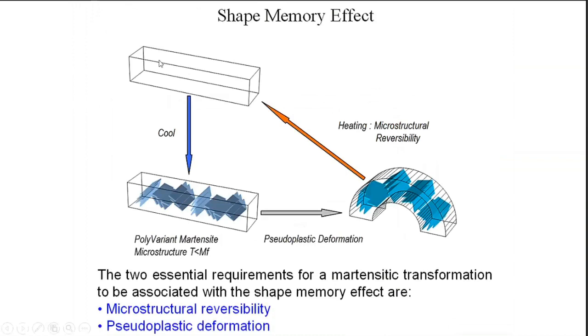So you start with an austenite, let us say a crystal, and when you cool it, you get a polyvariant martensite microstructure. What this polyvariant means is you have a lot of orientation variants. We said up to 24, and you've seen an example in the case of copper, zinc, aluminum, and nickel titanium. You have a lot of variants in the microstructure which form the self-accommodating martensite. And what you've done is pseudoplastic deformation. We've done a deformation which is very different from conventional deformation, and you've got a macroscopic shape change, as you've seen in the case of the flower, which was crushed into a bud. But when we heat it, there's a microstructural reversibility wherein all these grains of all these orientations of martensite coalesce and give the original grain of the austenite.